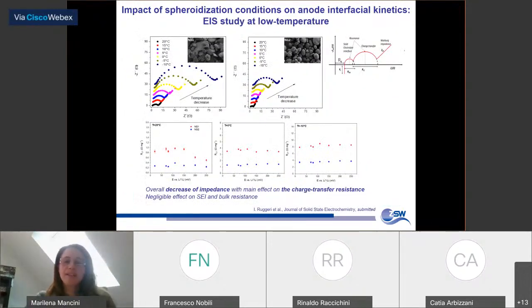calculations. What we can see from electrochemical point of view is that indeed the material which shows more defects on the surface and more oxygen-rich chemistry correspond to material which offer a lower impedance response in half cell measurements. And by calculating the different parameters out of the impedance analysis, we could see that the charge transfer resistance is quite lower for one sample compared to the other one in a quite large range of temperature. We have investigated these parameters between 20 and -10 degrees C. And you see the charge transfer drastically reduces for the sample Ng2.